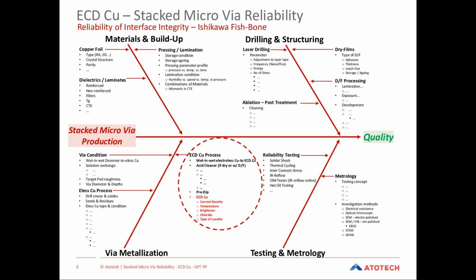And therefore pre-treatment is very helpful, but you have to be careful when you use any kind of cleaning chemistry. It is very easy for cleaning chemicals to get into the holes because the wetting capabilities of cleaners are often very good nowadays. But on the other hand, you also have to rinse the holes very nicely and very well thereafter. If there's some cleaner remaining in the microvia and on the target pad, this is then again a starting point for adsorption and increased contamination of this interface. So pre-treatment is very important, but rinsing is also a very important part of this.